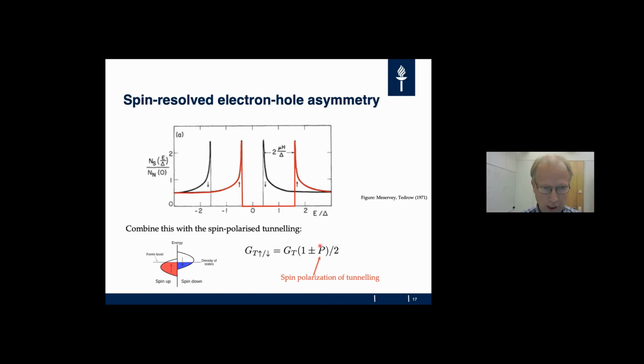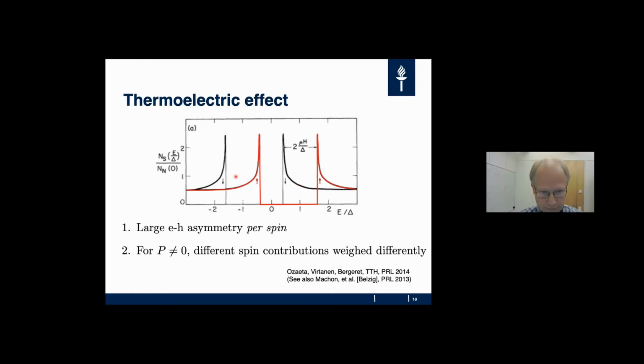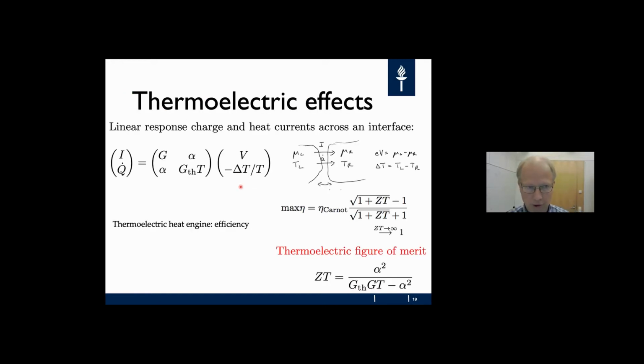If you have a finite spin polarization of tunneling, you weigh these different spin components differently, and this means you can actually resolve this electron-hole asymmetry. This actually leads to a thermoelectric effect, and I try to describe it a bit here.